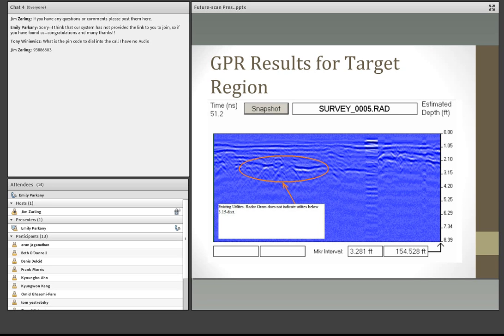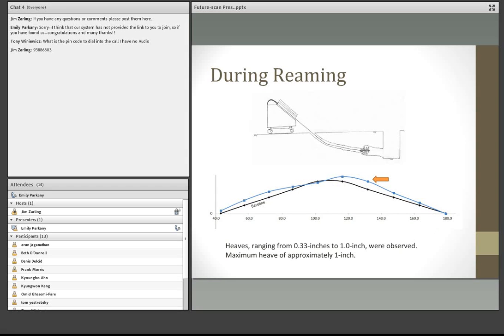And so what you see here is at about depth of 2.5 to 3 feet. There was a whole lot of scale. And what the GPR actually picked up were the utilities that were lying over top of the actual pipe. And so some reflections of the waves there did not allow us to see the pipe or any of the target voids that we installed. So that was a little bit disappointing, but also a little bit enlightening. Those were our GPR results.